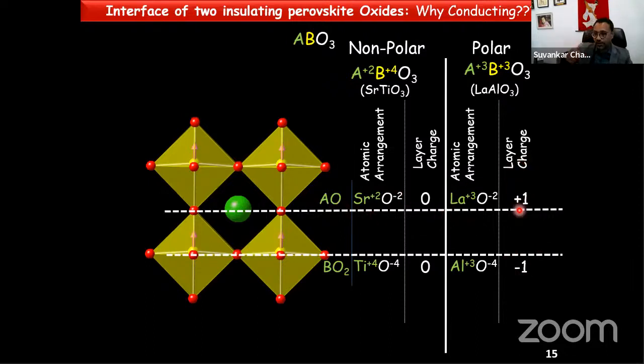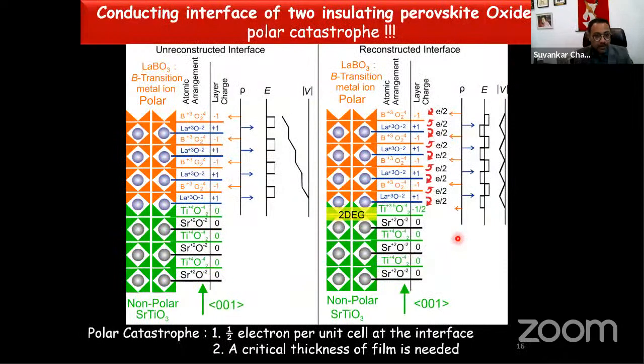So you now have +1 and -1 charge. This is known as a polar perovskite oxide, but overall it is charge neutral. Now one can easily show that if you make an interface of a polar and non-polar material, then you have at the interface a charge discontinuity, which gives rise to an electric field that looks like a step-like function, and the corresponding potential is now diverging.